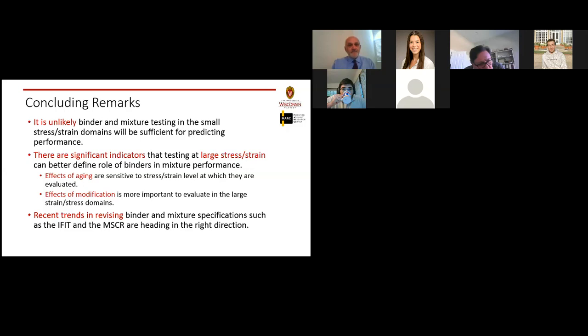You know, what I learned from your explanation for the fatigue test is that thick asphalt layers can be tested in the low strain domain, while thin layers should be evaluated in the highest strain domains to capture the real behavior of the mixture in the field. I believe that wheel tracking tests such as Hamburg wheel tracking have a stress domain, like 100 PSI, almost equivalent to the stress domain that we have in the field. What should we do for the wheel tracking test in terms of a stress strain domain?